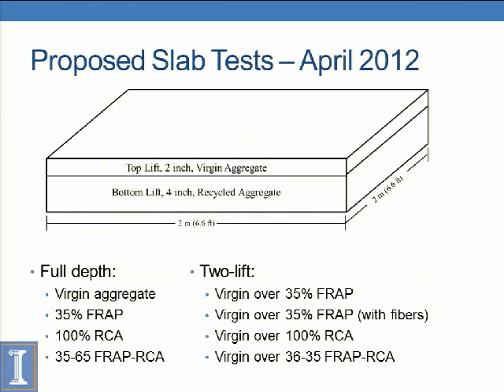And with that, I'd like to bring up, we're doing slab testing. We will be creating slabs probably sometime in the next few weeks here. If anyone's interested in helping us cast some slabs, we could certainly use your help. Pretty much what we're doing is we're testing this two-lift design that's being used by the Austrians and also what was used at the Kansas DOT study. Two-lift is also what the tollway is going to be using on their test bed project this summer. So we'll be casting some 4-inch bottom lift with recycled aggregate, topped with a 2-inch virgin aggregate. So please see me if you're willing to help out with that.